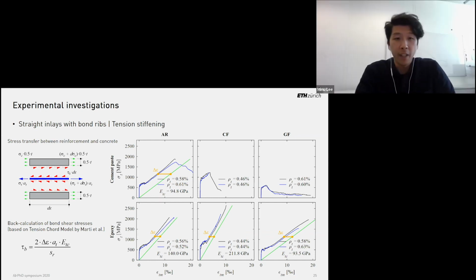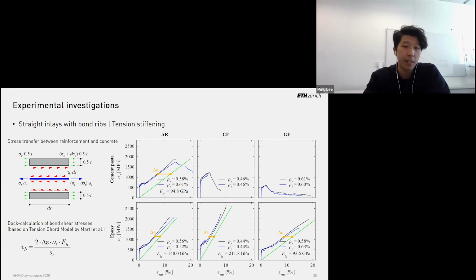Can you just give an explanation on that? So I think the biggest difference between the cement paste and the epoxy resin for the coating or impregnation of fibers is that, already from visual inspection of the broken fibers after we had tested, we could see that the cement paste is really just a coating on the outside layers of the rovings and does not fully penetrate into the rovings, and therefore the stress transfer within those yarns really depended on interfiber friction, which is quite low.